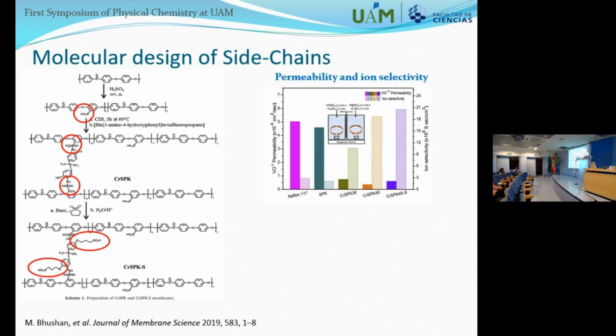So what they do with this, they did the synthesis, then they check the permeability and the ion selectivity. The permeability are the filled bars and the ion selectivity are the dashed bars. And what we can see is that when they have an appropriate cross-linking and then the sulfonation afterwards, they really enhance the membrane properties, reducing the permeability and increasing the ion selectivity.